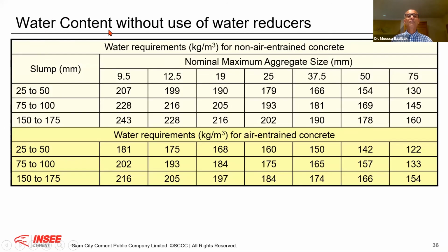Okay, now, if I take the slump, as I said, very often, you need with a set of material to do this type of experiment. But you can take this table to start with. It's a very good table. Very often I use it. It works very well. For example, if you take 150 to 175 millimeter slump for non-air, if I have a concrete of 25 mm, I need to put about 200 liters of water